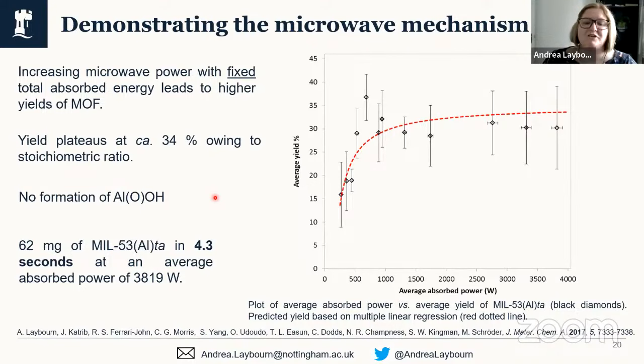So we went ahead and synthesized MIL-53 aluminium by changing the way in which we were delivering this energy. We fixed the energy and changed the power and the times to deliver that same energy, and looked at the yield and then the properties. On this graph, I've got the average yield plotted against the average absorbed power. Note that this is the absorbed power rather than the applied power, so we were measuring the power being absorbed by the reaction mixture.